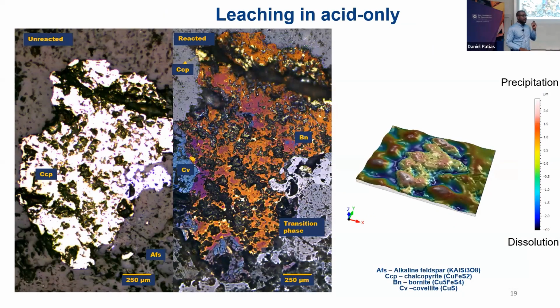Some results: first, leaching in acid only. If you leach in acid only, what we observe from the reflective microscope is that your fresh surface shows bright yellow chalcopyrite with alkaline feldspars. After 30 days of leaching, what we observe is that your chalcopyrite is apparently not leaching — rather it's transforming into several phases. It transforms into bornite, covellite, as transition phases, with apparently nothing happening to your feldspars, or maybe something, but we don't see that in these images.